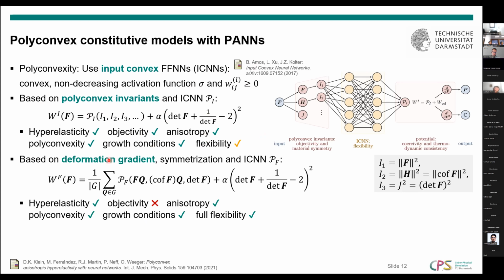Then we also had another idea where we directly use the deformation gradient and the symmetrization operation that you saw on the previous slide. So now basically our strain energy function is given in terms of this input convex neural network P of F, which takes as an input actually 19 coefficients, which are F, the cofactor of F, and the determinant of F. We have the symmetrization operation and this analytical growth condition operation.